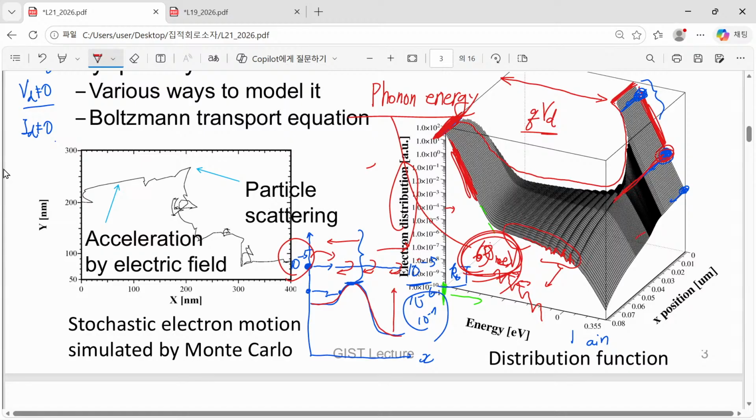So the transition from this point to that position means that only a small amount, 60 milli electron volt, of energy is transferred to the phonon, and now it continues its motion, and it loses its energy once, and once again, and eventually approaches the sea of cold electrons.